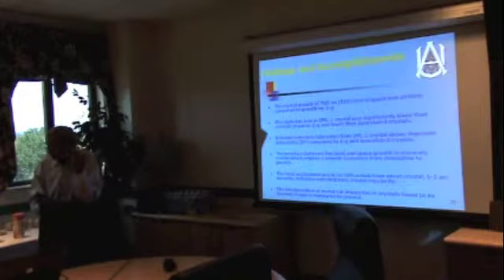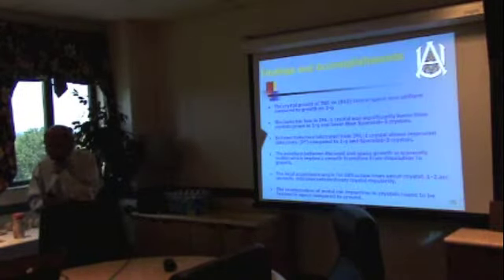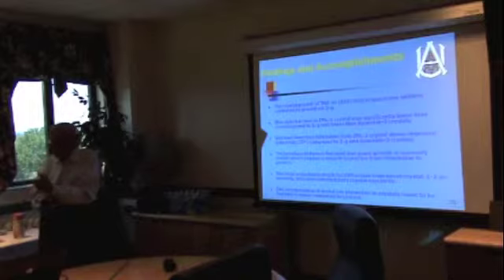So as soon as I saw, all the NASA guys were there, astronauts were there, and I said, oh, looks like the cell does not behave very well because it has some doped crystals at the bottom of it, which were not my crystals, randomly grown. They said, how do you know? I said, we know because we have done crystal growth of dopants with TGS. So we took those crystals out and measured their properties. We did an optical absorption technique to measure what their content was. And we were right.